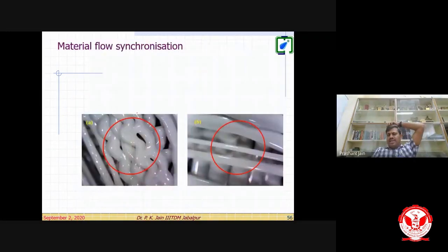Right? Yes, sir. See, in another situation also, if we do not control the flow properly, this kind of situation may happen. If the melt flow is higher but your speed is less, what will happen? This kind of waviness will come, and this kind of gap will be created. Similarly, here the diameter is very high, and here the diameter is very small.